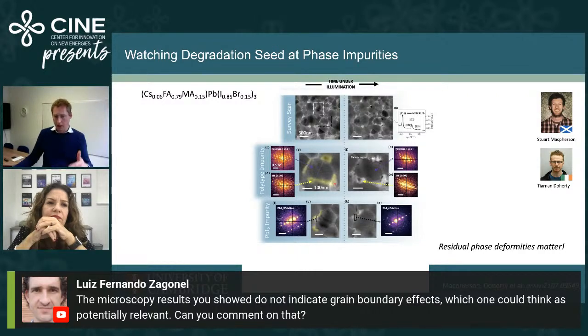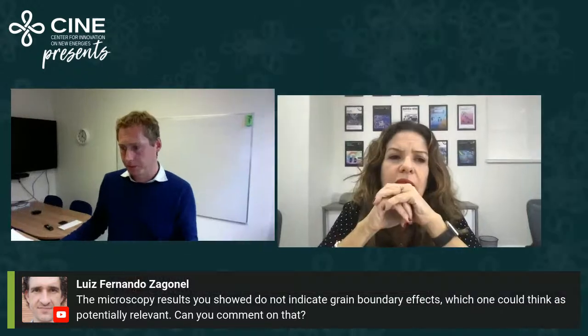So I would say that they are related to the grain boundary, but maybe not in the classical way you might expect. In the methylammonium systems, particularly the early ones, it did look like the grain boundaries were a lot darker in luminescence than the surrounding regions. That seems to vary a bit with processing. Some grain boundaries can actually be brighter, depending on what the passivation is around those boundaries. So I think it's quite complicated and quite composition dependent, but overall boundaries are somewhat problematic.